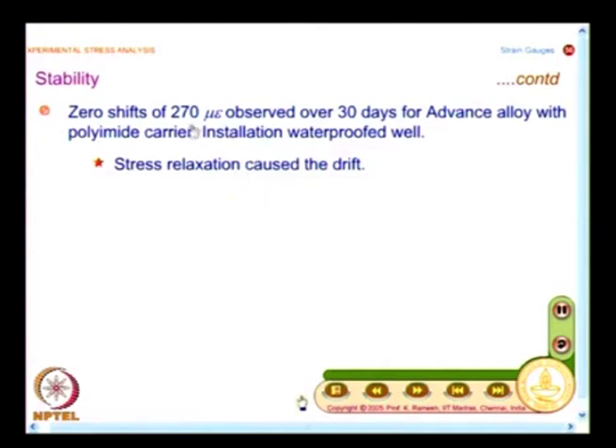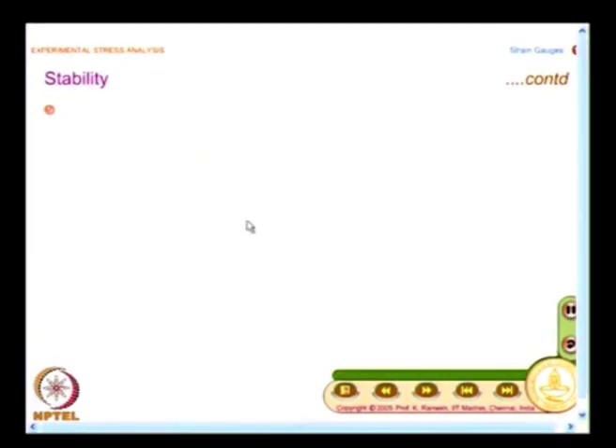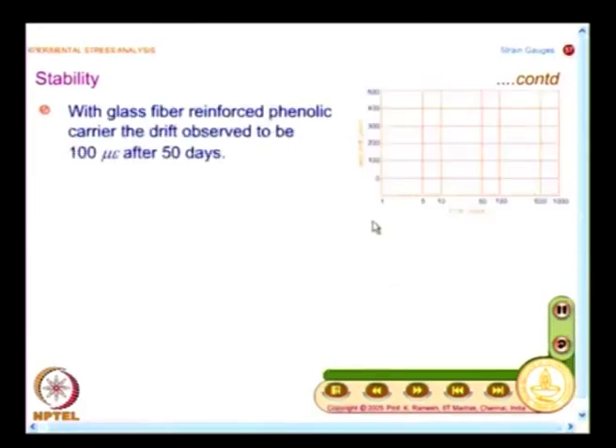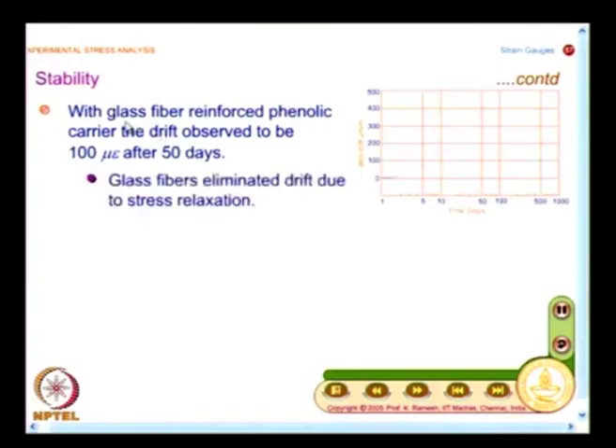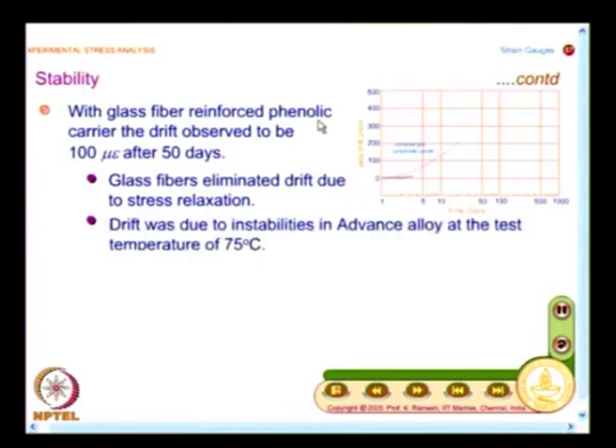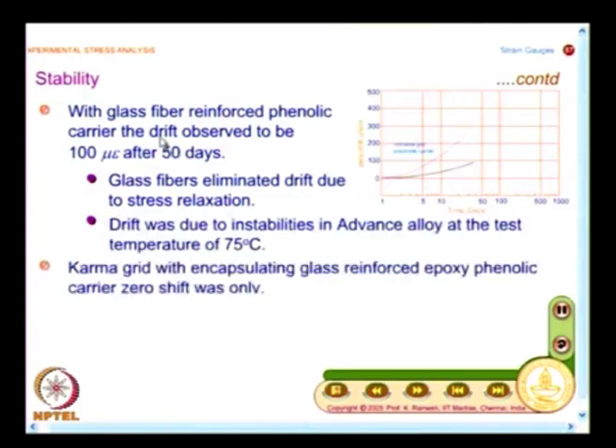And when you are making a measurement, 270 microstrain is very high. If the zero shift itself is 270 microstrain, then what level of confidence will you have in the final measurement? So, for a given application, you need to find out, have you selected the right combination of strain gauge alloy, carrier as well as the adhesive. And you see in stages, initially we saw 270 microstrain, which is very bad. Now, I go and improve the carrier. Instead of polyimide, if I use a glass fiber reinforced phenolic carrier, the drift has reduced from 270 microstrain to 100 microstrain even after 50 days.